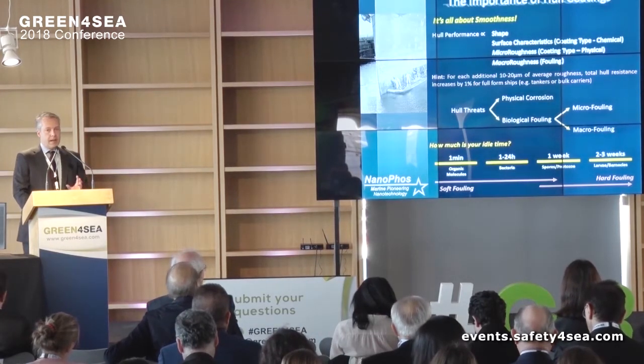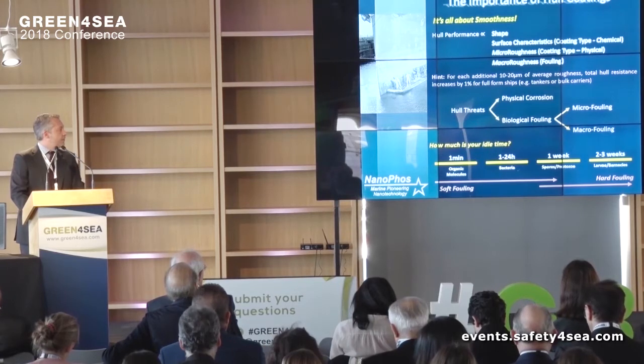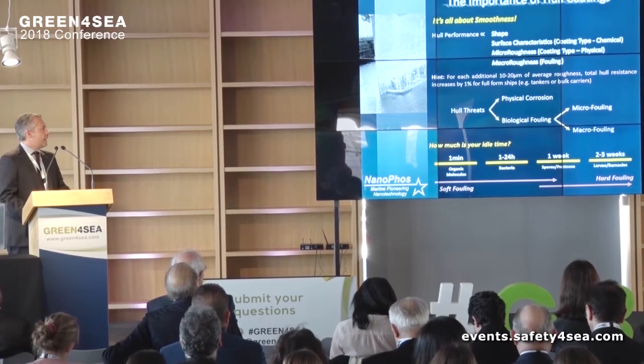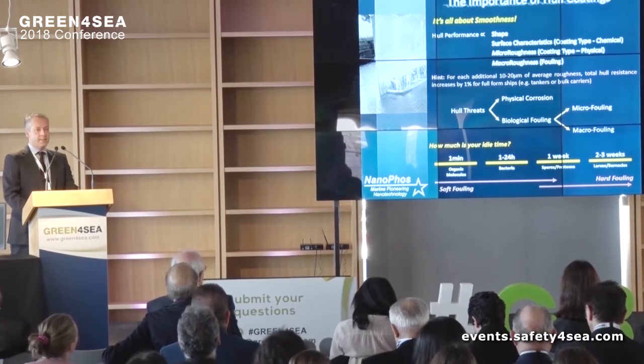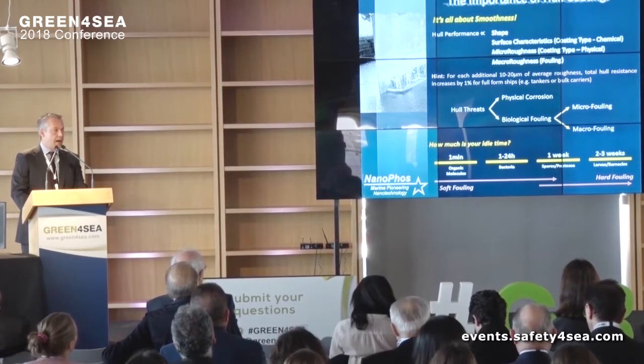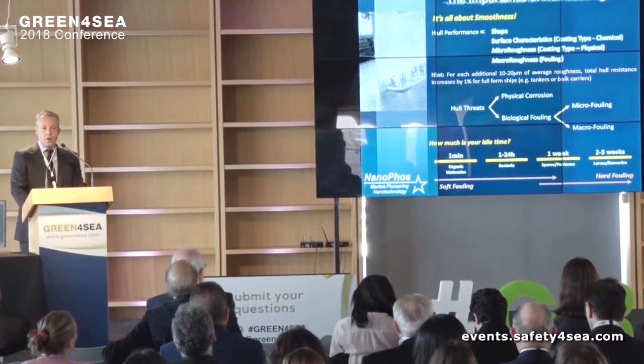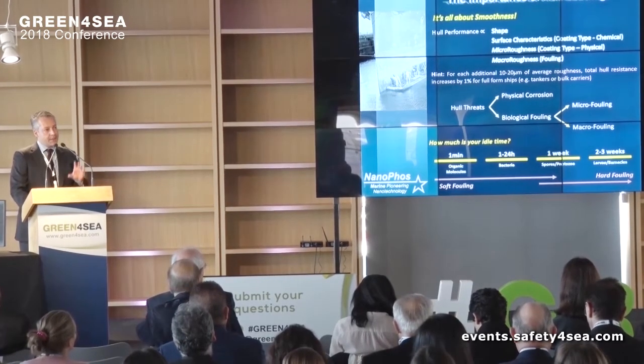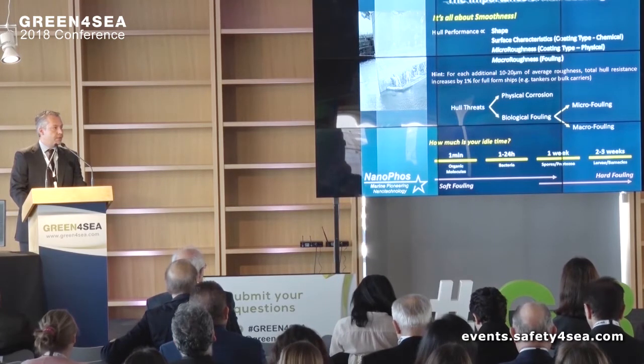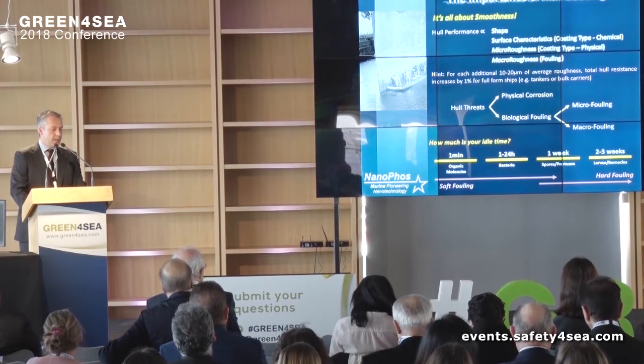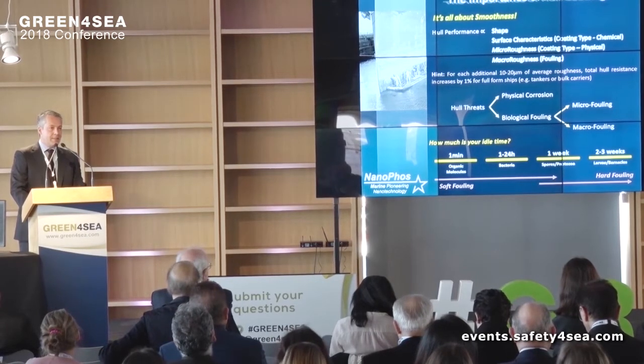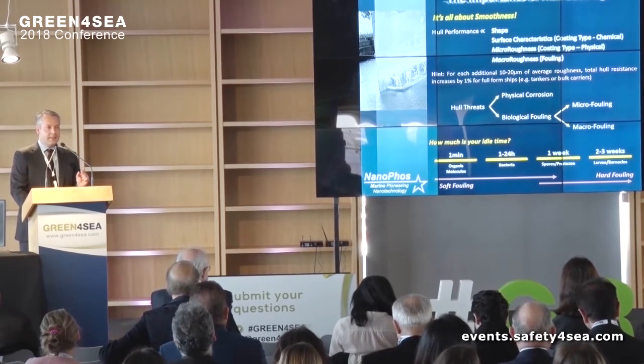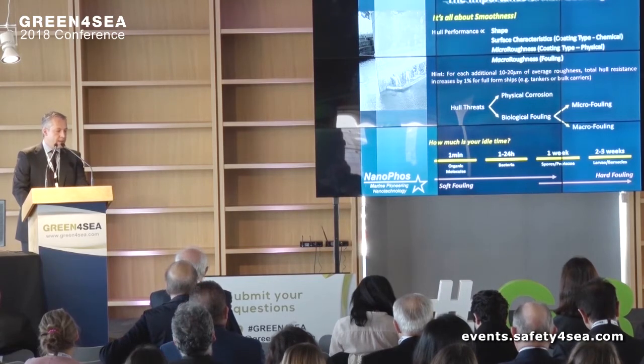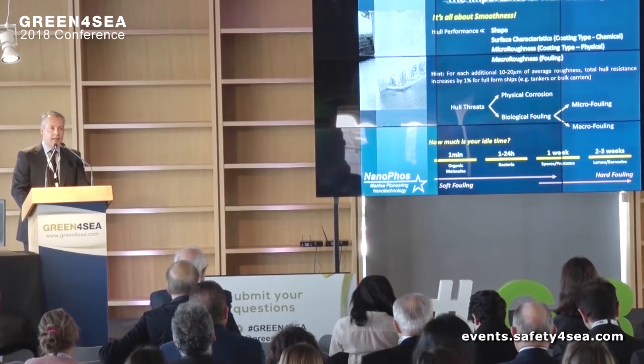Let's talk about hull coatings. Actually, the performance of the vessel is analogous to its shape, the surface characteristics, the micro and macro roughness. Apart from the shape of the hull, all other parameters can be changed during the operation of the vessel. So this is what we have to focus on. Just keep in mind that a change in roughness of about 10 to 20 microns during the operation of a vessel might increase the total hull resistance by 1%.